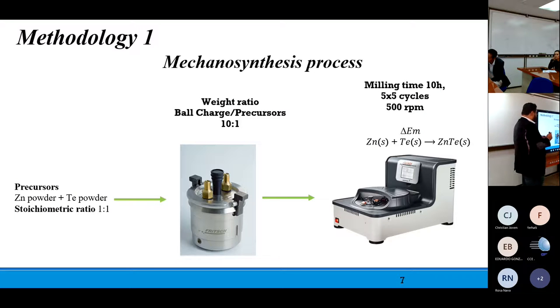Well, the methodology for the mechanosynthesis process is the following, as in this slide. We use zinc powder and tellurium powder precursors with a stoichiometric ratio of 1:1. We use a weight ratio of ball charge to precursors of 10:1, and these precursors and the balls were added into a milling jar. This milling jar is placed into the milling machine, with the following conditions: the total milling time was 10 hours with a cycle of 5 minutes for milling and 5 minutes for rest, with a speed of 500 RPM.